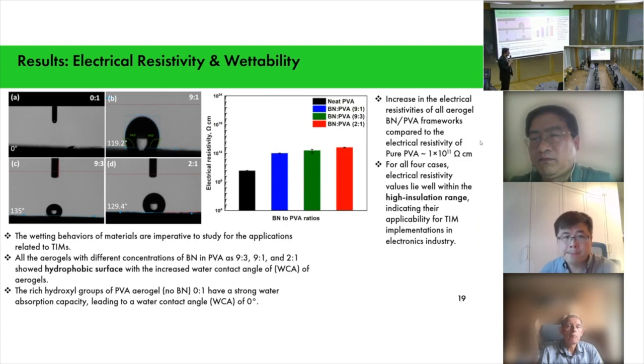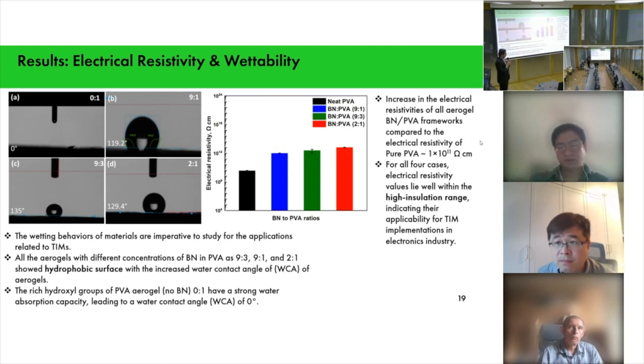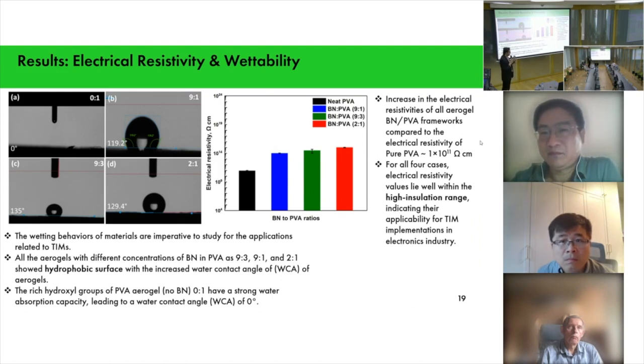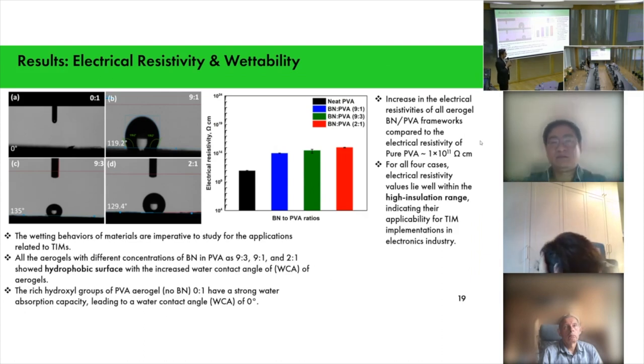Yeah, I think you are talking about the coefficient of thermal expansion in the polymer system. When you talk about polymer, like epoxy resin, it has some coefficient of thermal expansion. When you talk about the filler, it has a different one. So the idea was to develop such a system in which, by using this interface, you can transfer the heat or phonons. The interface is just of nanometer thickness. Either it acts as a bridging effect, so you transfer the heat, or it scatters the phonons or the heat, or it can be absorbed. So in the future, if you want applications where you need to check the coefficient of thermal expansion, then it is a good thing to do research on.